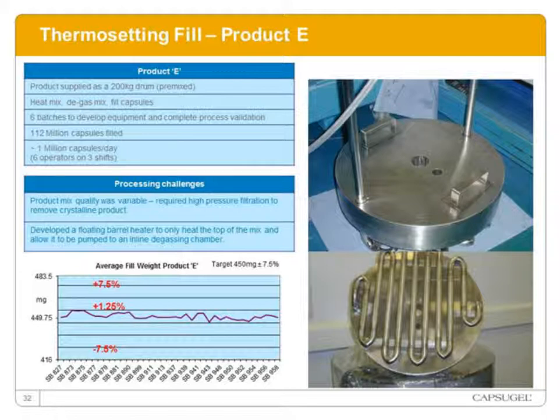Because of the requirements to increase our manufacturing speed and capability, we actually designed for this product a floating barrel heater, which was a novel design. So there's a heater which sits on top of the mix, and as the mix melts and is drawn off into a degassing chamber and subsequently onto the filling machine, then the heater gradually moves down the barrel as the material melts. So this is a very fast, efficient process and allows us to fill 1 million capsules a day. And we've filled so far 112 million capsules.